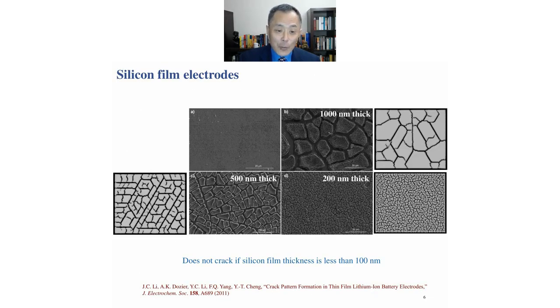Not surprisingly, therefore, the silicon electrode would crack after just a few cycles. As showing here are some of our experiments, with increasing thickness of the silicon film, the cracking pattern changes from nucleation-dominated behavior to crack growth and propagation. And that change in the cracking pattern can be captured by a very simple computer model showing on the side.